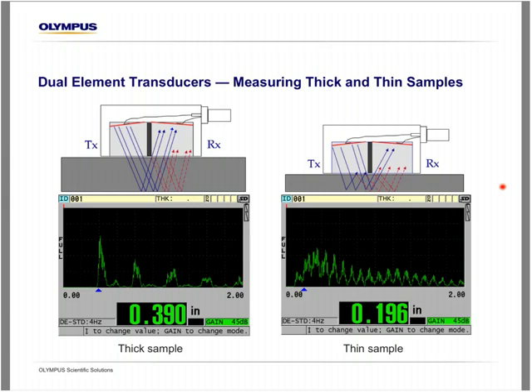So at thicknesses greater than the focus point of the dual element transducer, the first back wall is going to be the highest amplitude echo. But if the thickness is below the focus point, then that first back wall is not necessarily going to be the highest amplitude echo. So this is why doubling typically occurs on thin samples and not so much on thick samples.